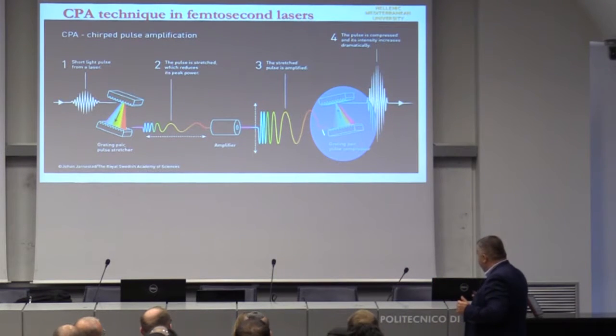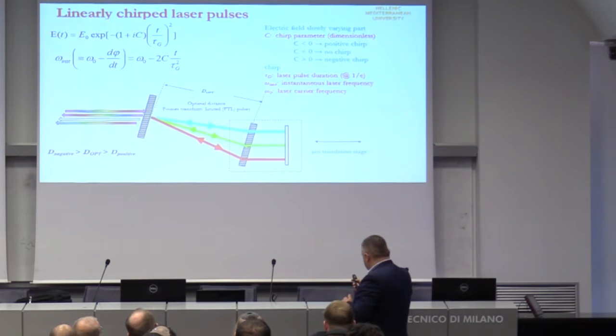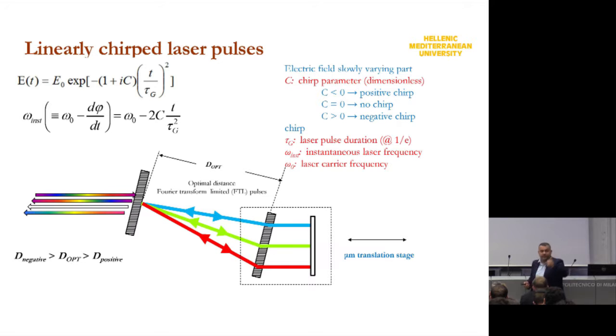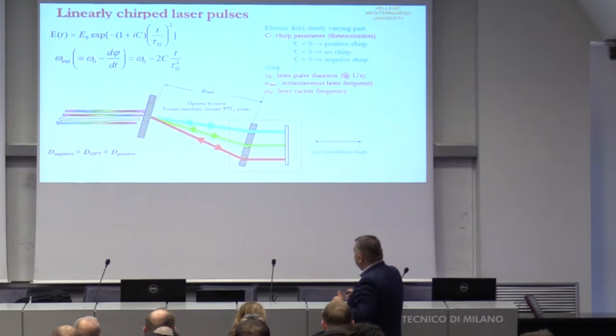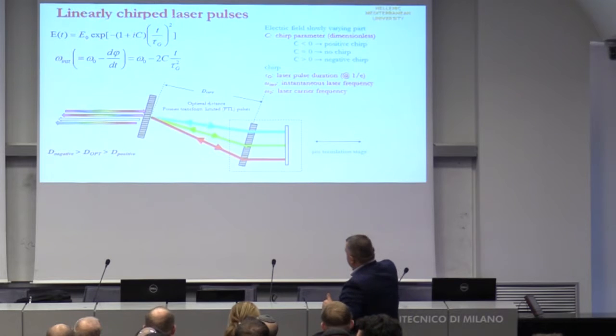And in our lab, we can play with these two gratings, the distance between these two gratings. If you play with the distance between these two gratings, you can produce Fourier limited pulses. Positive chirp means the red photons of the pulse come first and the blue after, or negative chirp where the blue photons come first and the red after. So we can play with this kind of chirp parameters. Here is the chirp parameter: negative C means positive chirp, equal to 0 means no chirp, and positive C is negative chirp. These are the explanations.